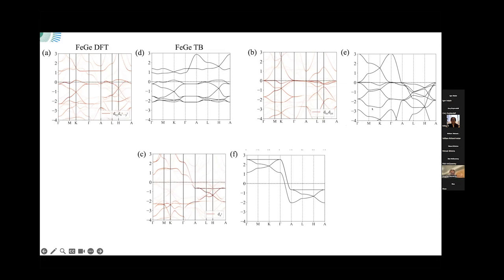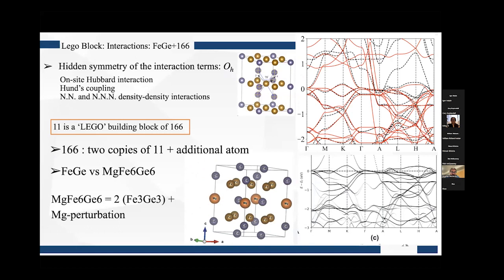So I would like to claim that these orbital models give you a faithful description of the physics, at least of the electronic bands, in FeGe, FeSn, CoSn, and many others. Because now, as Igor pointed out early on in this meeting, they're basically isostructural, so you can take this FeGe structure, put a lot of planes of FeGe, put some atoms in between them, and do perturbation theory and obtain the band structure of a lot of these 166 compounds as perturbations of this Lego block of FeGe band structure. And you can see clearly that they have the same features, at least en masse.